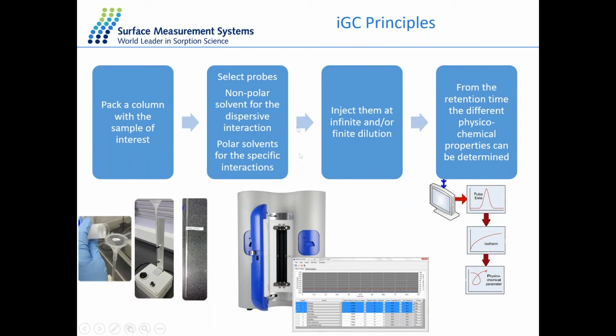We can then choose how to inject them. So we can inject them at very small concentrations, so infinite dilution, or much larger concentrations. We then start our experiment on the software, and depending on the interaction between the probe molecules and the sample, we would obtain different peaks based on different retention times, which we can go ahead and analyze.